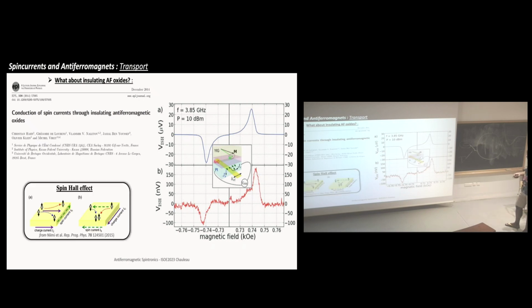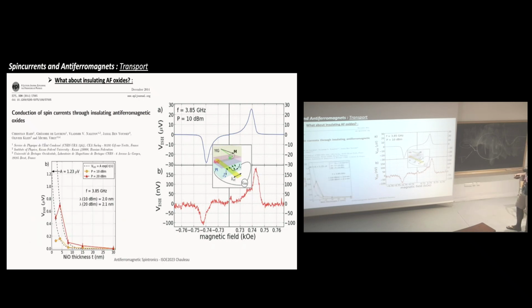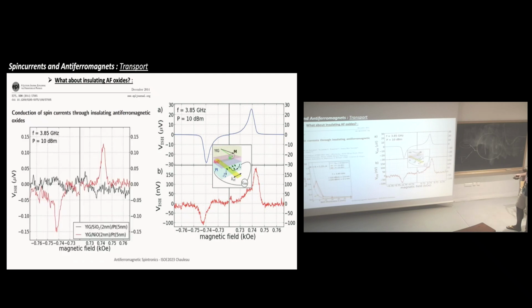So, okay, this is what I wanted to tell you. If you have a spin current here, it can be converted into a charge current, and this is what they are measuring there. But you already know that from the lecture on spintronics. And what they have done now, they have changed the thickness of the NiO, and then they could see a maximum. But after a couple of nanometers, they could not measure anything at all. And as a proof, they have changed NiO by silicon oxide, which is not an antiferromagnetic material, and you can see then there is absolutely no signal. So this is really the proof that the antiferromagnetic material, the NiO, could actually convey the spin current. That was one of the first proofs.